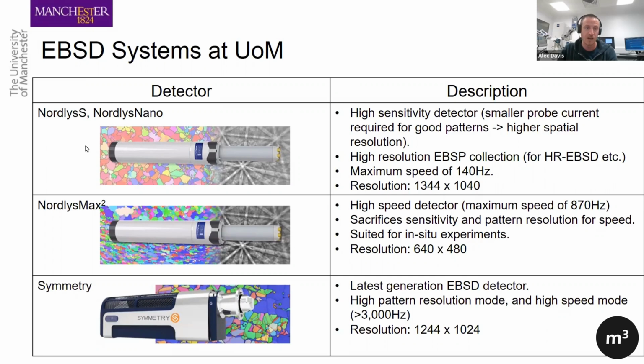We have the older CCD cameras. So we've got the NordlysS and the NordlysNano, and these are on our microscopes such as the Sirion and the Quanta 650. These are high sensitivity detectors, and they give good high spatial resolution. They have a maximum speed of 140 hertz. And when I say this, this means the rate at which they're collecting EBSD patterns, so the maximum here is about 140 patterns per second. And the resolution of this camera is 1344 by 1040.